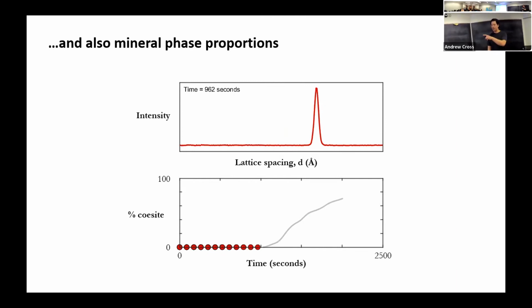So it's pretty neat. And in some of Rheoli's experiments, we've been trying to capture and quench the samples right as they're going through the phase transition, which at some of these conditions will happen within about 5 minutes. So it's really crucial that we're able to nail down where exactly we are in terms of volume proportions.